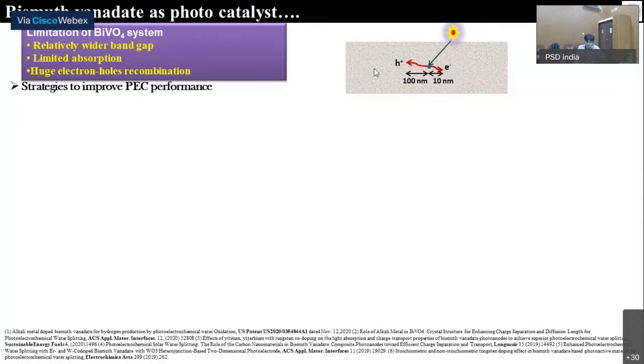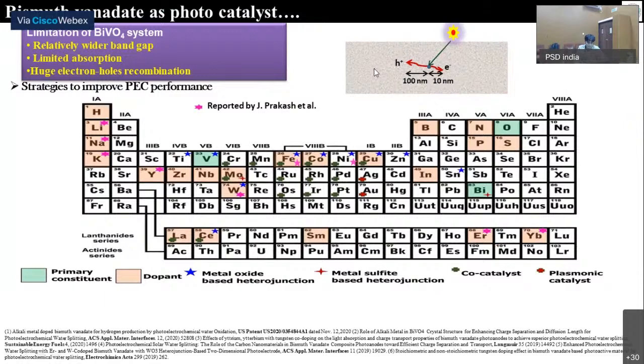So what are the strategies we can adopt to improve the performance of this bismuth vanadate system? I have shown it schematically using a periodic table. We have a primary constituent, bismuth vanadate. Now in this we can do doping using different atoms, whether on the lattice position of bismuth, vanadium, or into the interstitial position. Different elements have been tried and we have also reported in our lab.